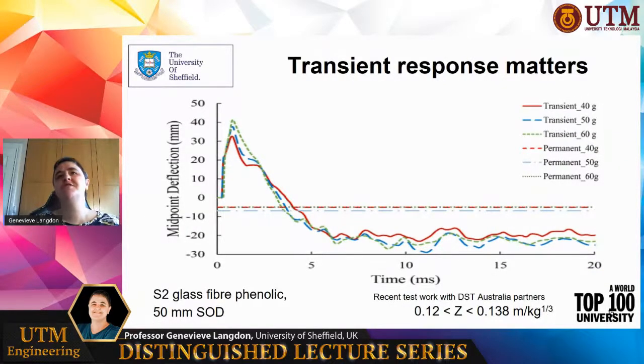The elastic brittle nature of FRPs means that the post-test deformations are very small, even though the failures are massive. This is because they lack plastic energy capacity. However, one thing it does mean is that just looking at the final form shape of the structure will tell you very little about its overall transient response. So you don't know what its maximum deflection will be.